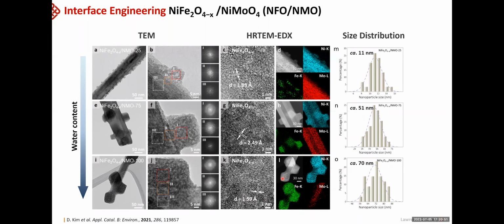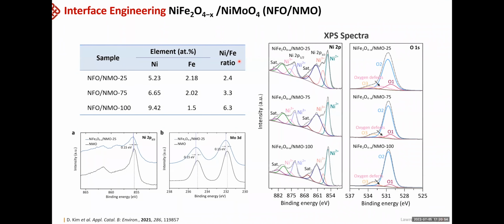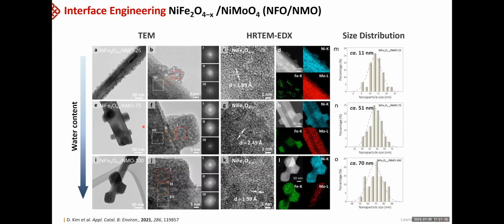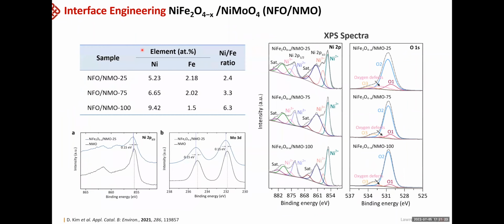What's interesting is that when we use XPS to analyze their composition, the nickel to iron ratio changes when we change their size. So this is the smaller one, which means it actually has more nickel iron oxide species on the surface. So you may think maybe the larger particle may have more iron species, but actually the smaller ones are more evenly distributed on the surface. So we can see more active material on the surface when we make them small size.